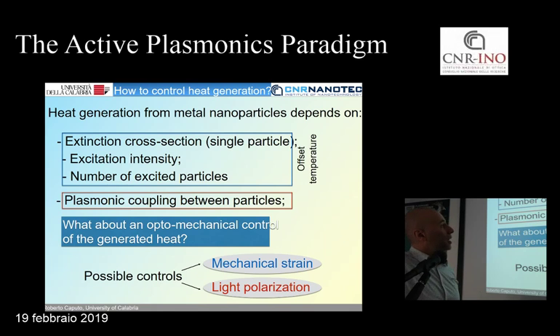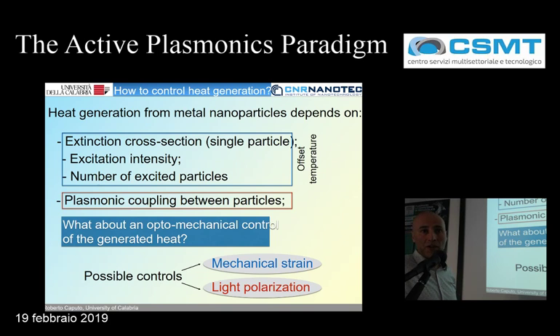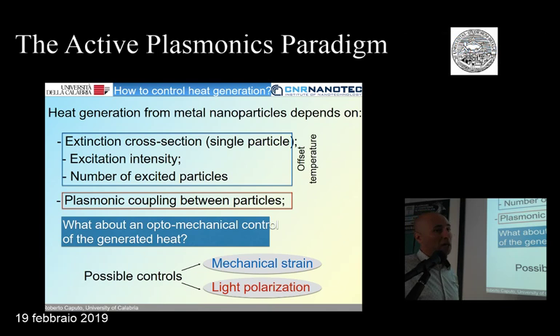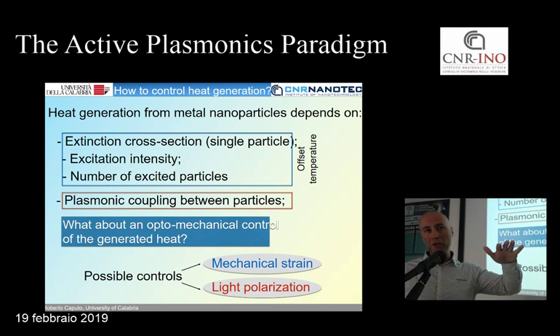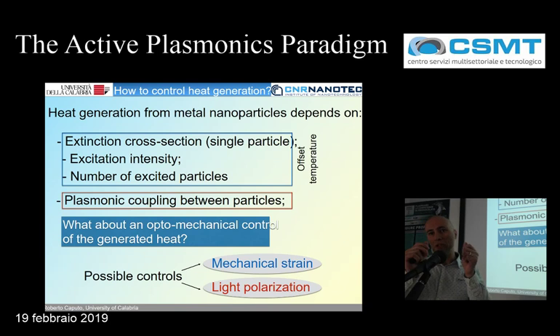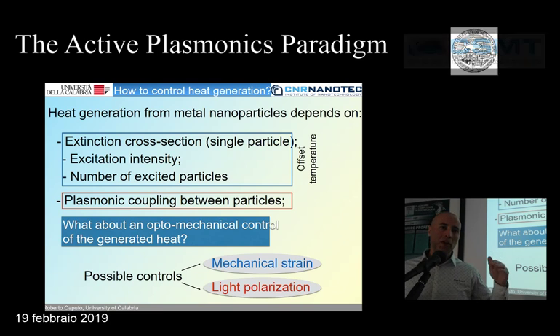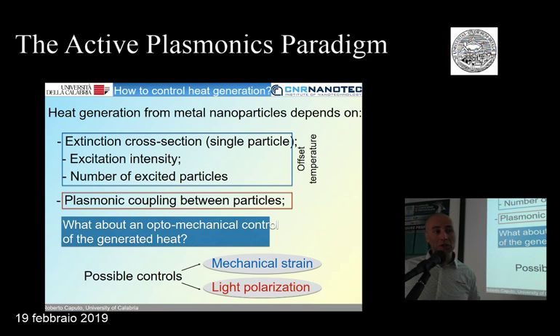So as we said, the absolute temperature of the system can depend on the single particle extinction cross-section, or on the excitation intensity, or on the number of excited particles. But if you fix these parameters and you apply an intensity of pumping, you will have a given temperature that we call offset temperature. But when you induce a coupling between particles by means of an external mechanical action, you can modify this temperature in a fine way. So this is what we wanted to demonstrate.